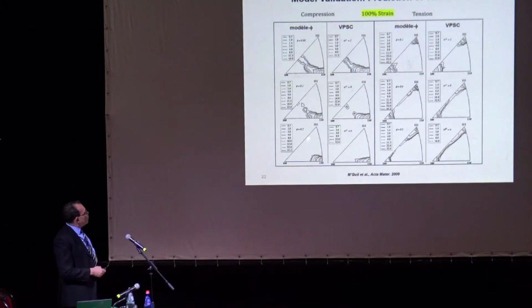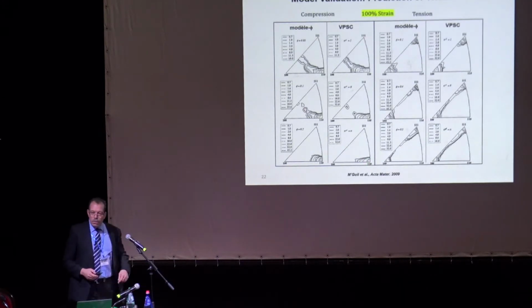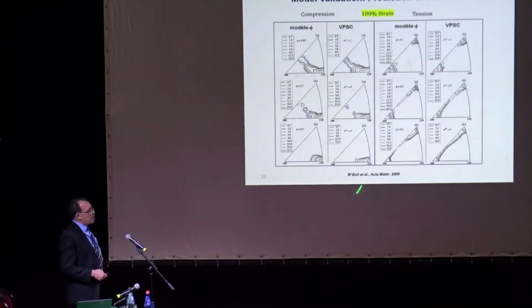If I go down here, this is n effective equal n. This is the tangent formulation. And we get this texture component at 100% strain. We can say that this is an FCC metal, and all the 110 are parallel to the compression direction. This is the texture component we get. And we get exactly the same thing if we take phi equal 0.2, an intermediate phi, not too small, not too close to the upper bound.